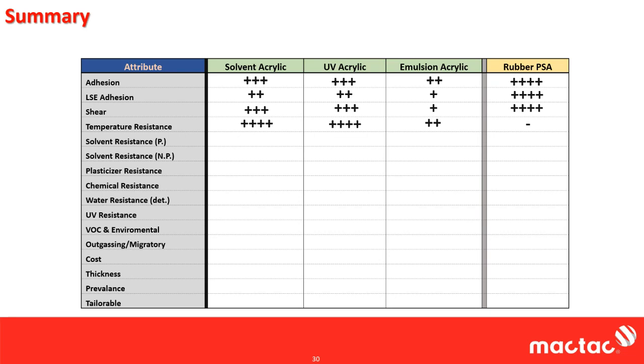Once you get some interaction, high molecular weight of the acrylics and some cross-linking, they're really never going to melt again. So solvent resistance, the P there is for polar solvents. Acrylic UV, pretty high. With acrylics and solvents, you can get them to swell. If you're bringing in polar solvents, this is your MEKs, your acetones, your ethyl acetates, your alcohols. They won't redissolve, but they will swell in those environments.